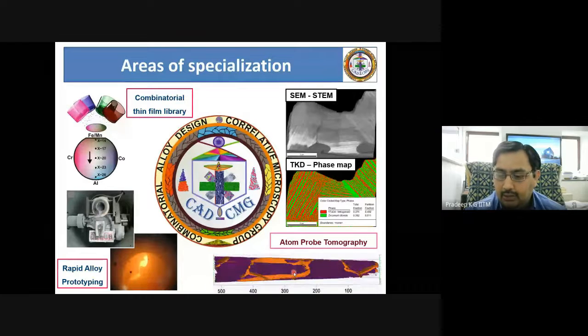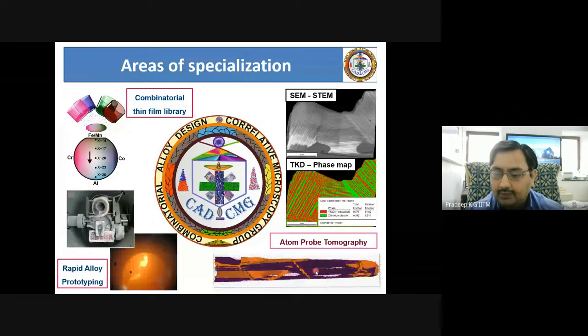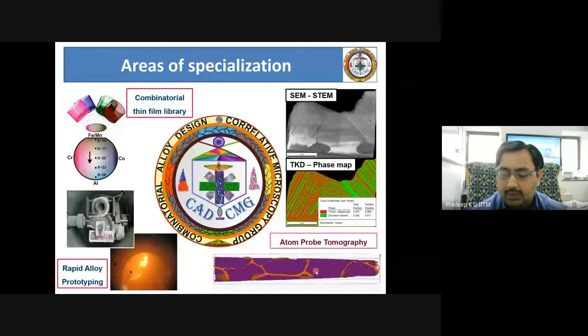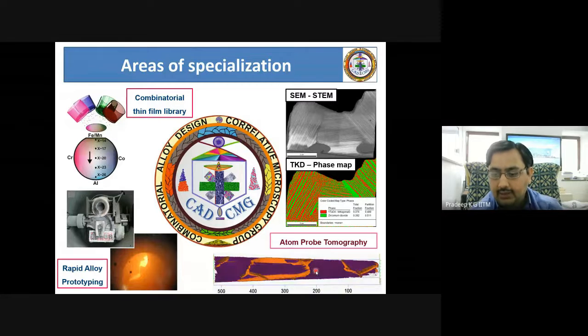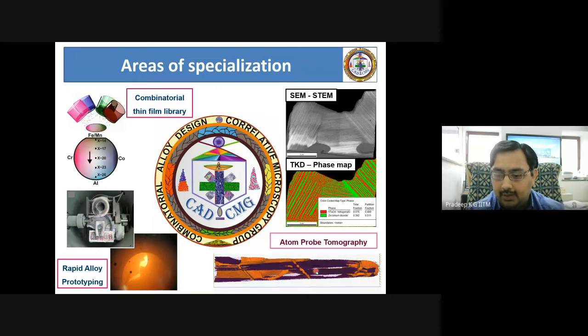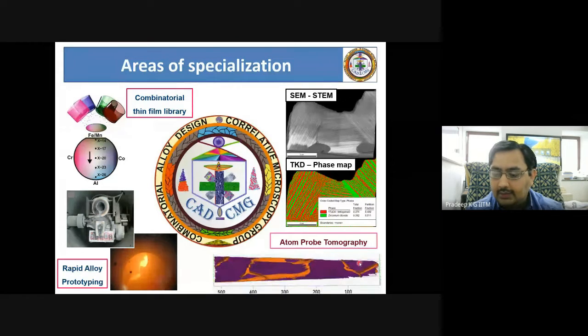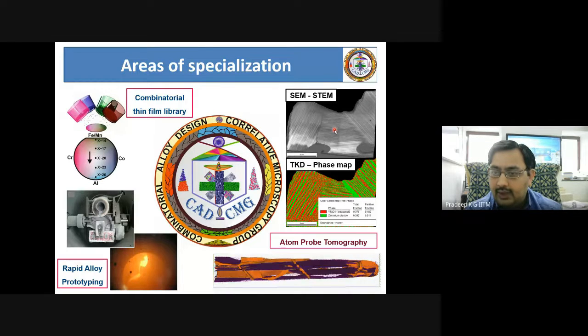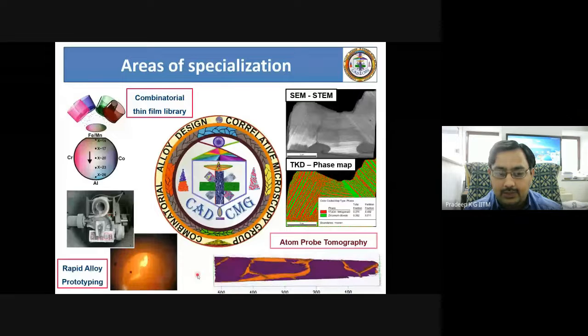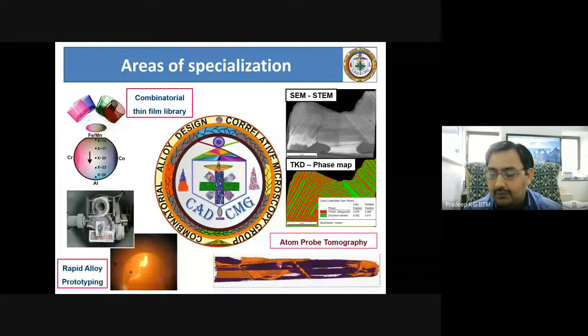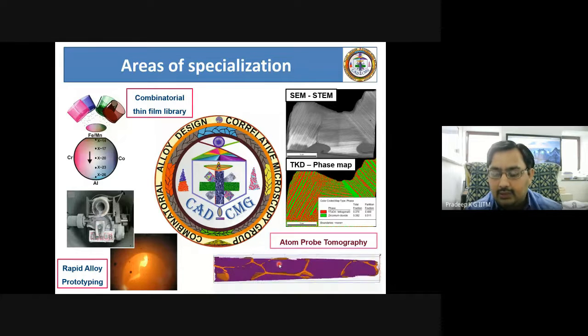So that means atom probe tomography is a tool that gives rise to the finest possible detail of chemical identification. That means even the parts per million of elements present inside can be identified, and all the elements that are distributed in the bulk material can be distinguished for their spatial orientation, because it is a three-dimensional analysis technique, and this enables us in visualizing the atomic distribution in 3 dimensions as well as the chemical concentration measurement at the most accurate method as far as possible. That means from a 3D bulk material, we have now techniques where we can look at their microstructure as well as their chemical distribution in 3 dimensions, so that we are able to interpret whatever materials that we have prepared with their finest atomic scale distribution detail, so that we are able to interpret their properties in a much better way.